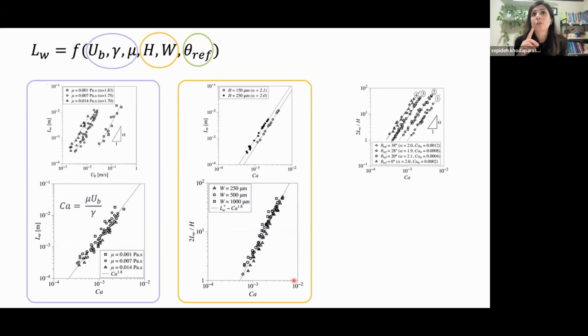But I said that the wetting of the channel does have an effect. And in fact, if you change the wetting behavior of the channel wall, you see that, again, the curves of the data are shifted in the log-log plot. So they're all still having more or less the same power law, but they're all shifted.